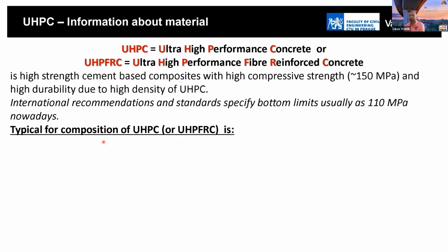You will see that the surface of this material is closed, so it is very important. By this closing of the surface, it is possible to limit the effect of, for example, chemically aggressive waters from chemical elements, and we can reduce the possible damage of the concrete elements. By the international recommendation, we speak about UHPC for materials whose compressive strength is more than 110 megapascal. Now it is defined.